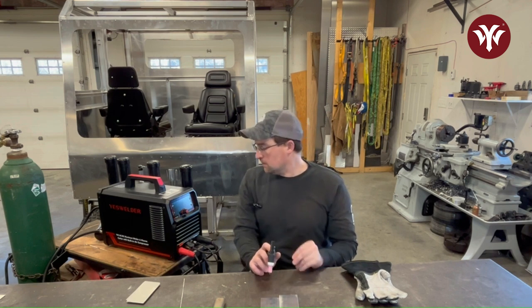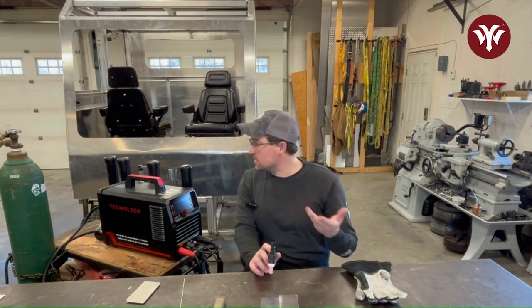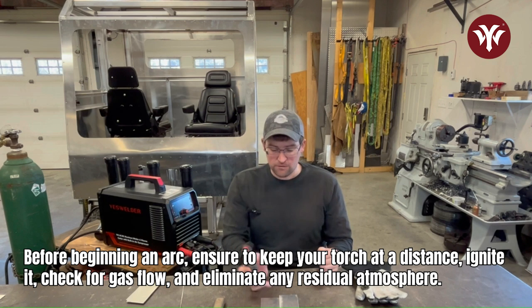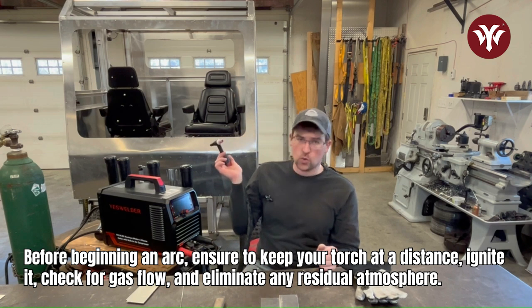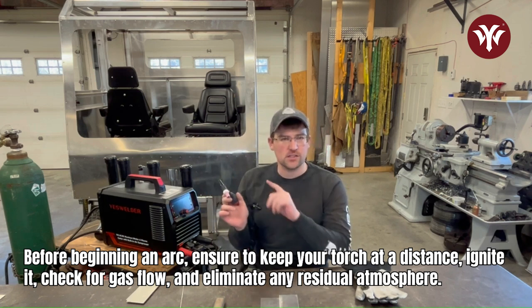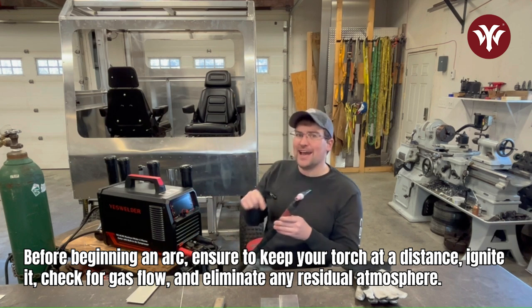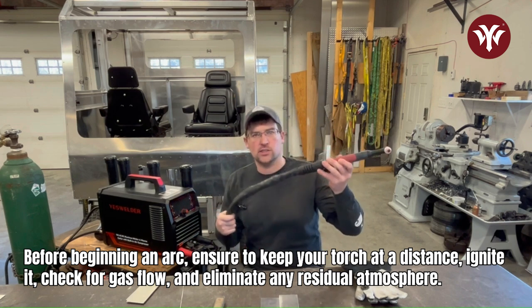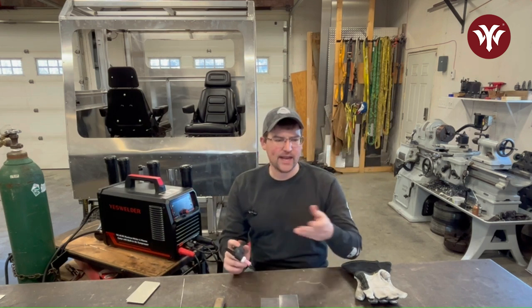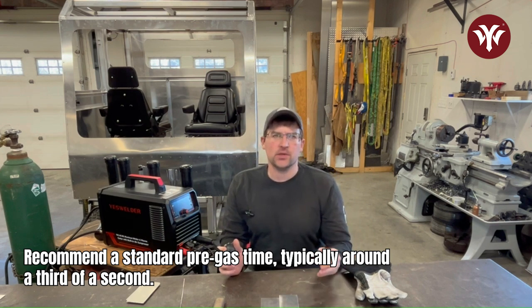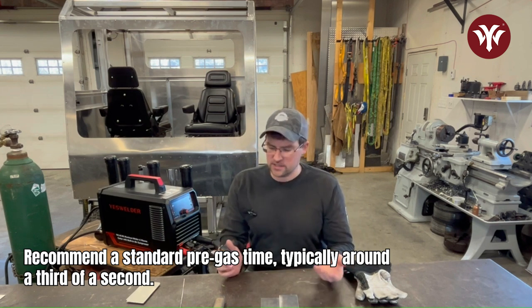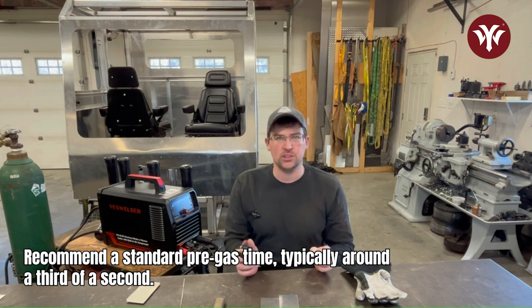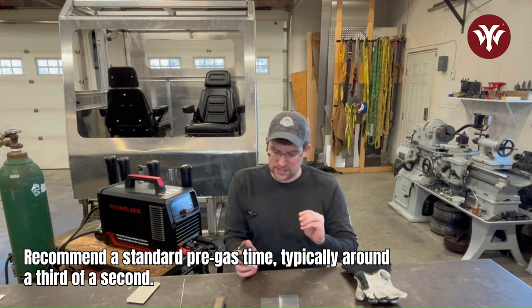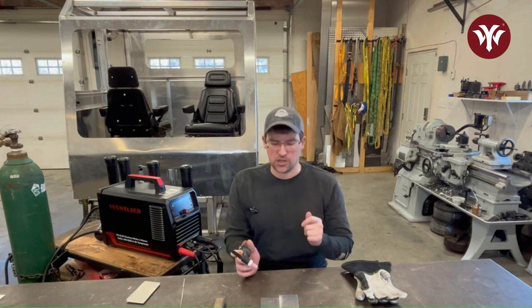So one of the things I suggest, if you haven't used the machine in a while, before you even start an arc, hold your torch away, strike it, listen for some gas flow, and purge any atmosphere out of your torch lead. So pre-gas, I was doing some reading. It's typically around 1/3 of a second. If you have purged your torch, that's going to be enough. It's going to get gas flow, the arc's going to start, and then you're going to be welding.